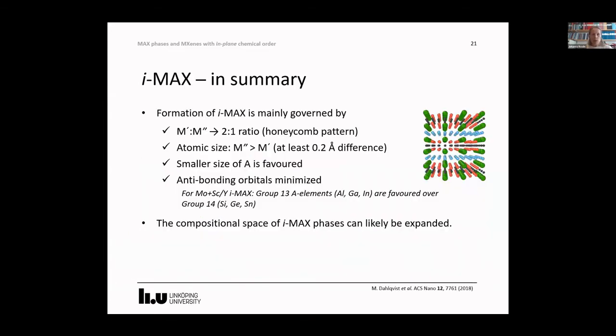So if we summarize what we know about IMAX to date, formation is mainly governed by a 2-to-1 ratio of the M elements. What I haven't shown today is that we've made a more detailed theoretical analysis. This analysis suggests that in order to form IMAX, we should have a significantly different size of the two M metals. We should also have a preferably smaller size of A, and the population of anti-bonding orbitals should be minimized, like for the OMAX phases.